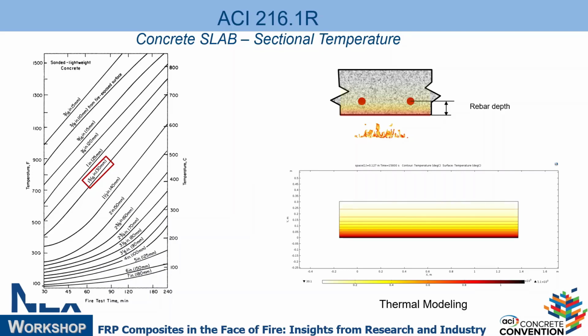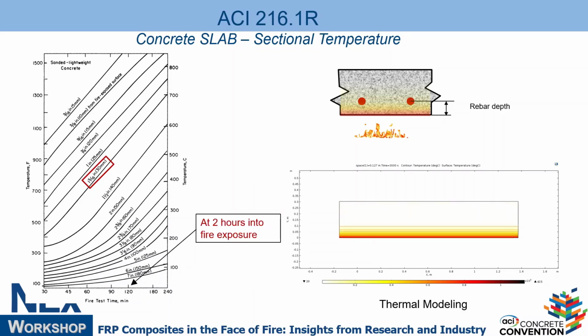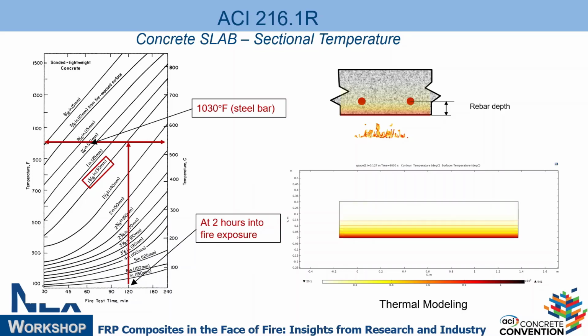This is intended to be for a slab. I'm just going to use this for a simple example. Most of these charts are based on the distance from the outer surface to the centroid of the bar. We don't look at the cover, we look at the distance to the centroid of the bar. That is the depth of the rebar. So let's say I have a slab and it's approximately 1 3/16 in., 30 millimeters. At 2 hours, the temperature of that bar is close to, let's say, 1,000 degrees F plus or minus, 1,030 shown there, or close to 550, 570 C. So these charts can help you figure out the temperature of the bar, right? I'm going to use that later on, so keep that in mind.